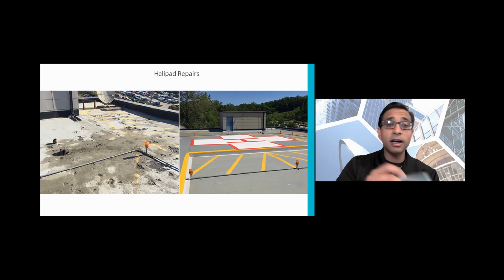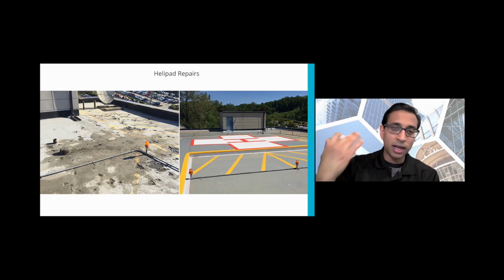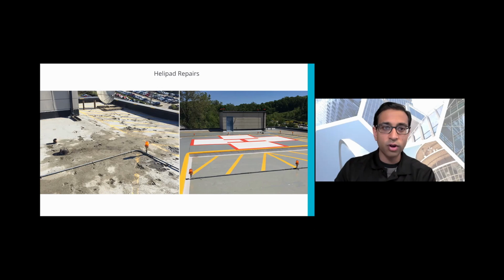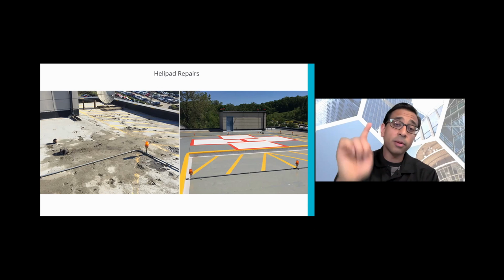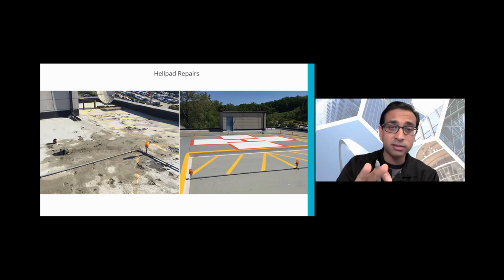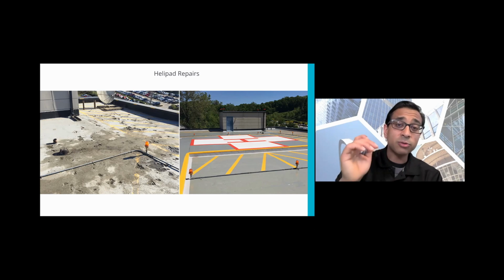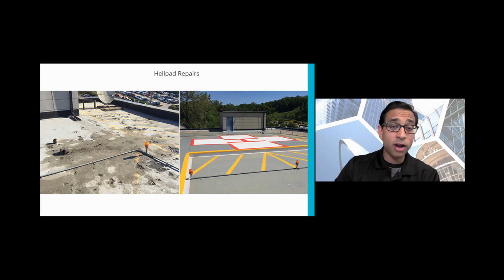So rather than cutting out sections of the helipad, pouring in the concrete, waiting for it to set, painting over, and just doing that endlessly, use an epoxy. With an epoxy, you can go right over, smooth it over. It'll fill in. Here's an interesting tidbit. Compressive strength of concrete, after you let it sit in perfect conditions, is about 8,000 PSI. Epoxies within 24 hours will be between 12 and 14,000 PSI. So within 12 to 24 hours, you're going to have a stronger material, and you're going to have it up and running.